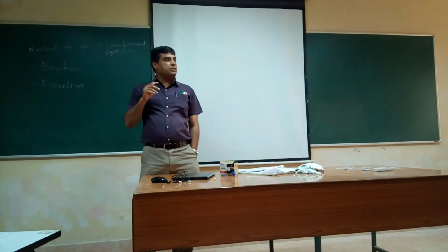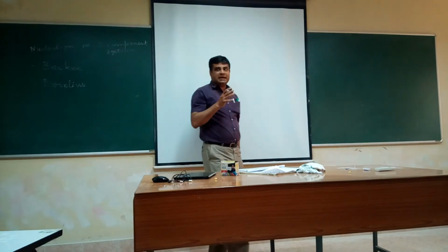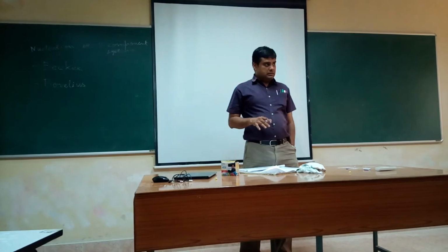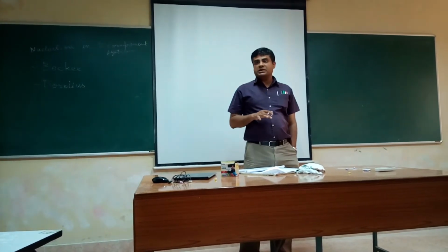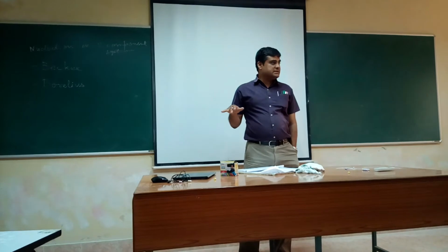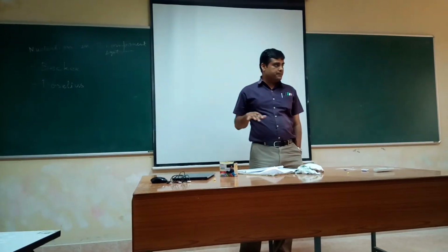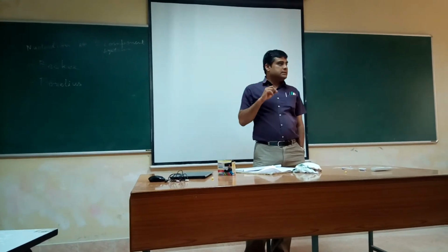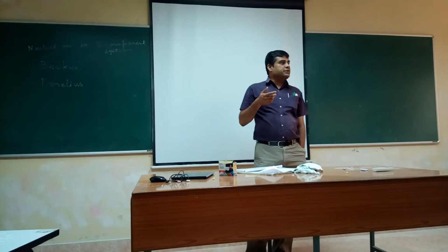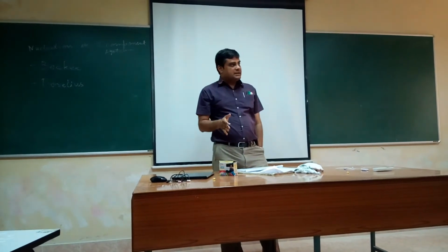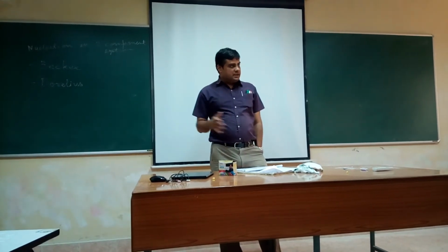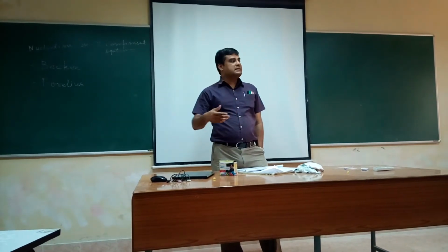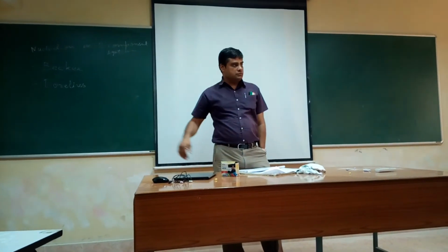So we had the curve of delta G, the Gibbs free energy of formation of the embryo, versus, not the size, what was on the x-axis? The composition of the embryo. And we found the delta G star. So any embryo of composition above that x star will be stable, because further addition of an atom will make the Gibbs free energy go down.